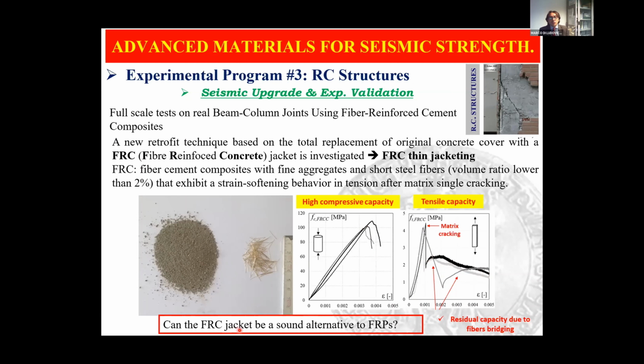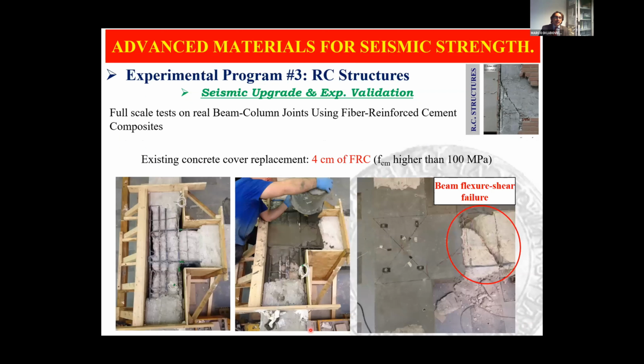So the question was, can the FRC jacket be a sound alternative to FRP? And so we removed the concrete cover on the second specimen. We applied this new concrete cover, which works also as a repair and strengthening solution. And then after the test, this part was completely undamaged. The cracks developed on the beam.